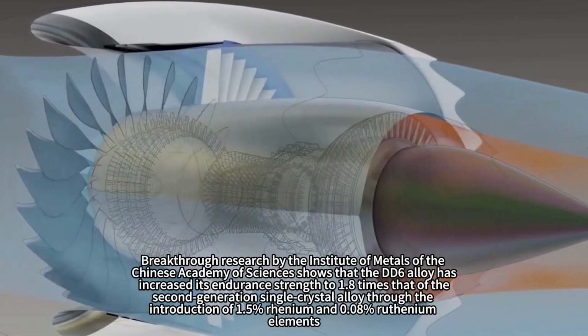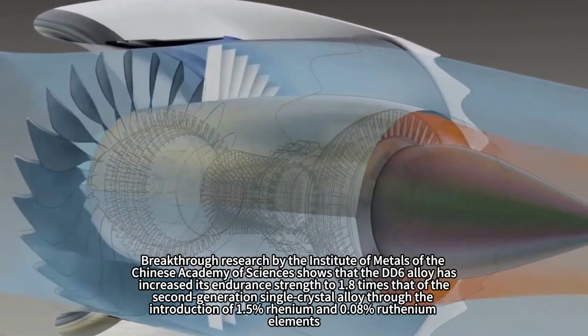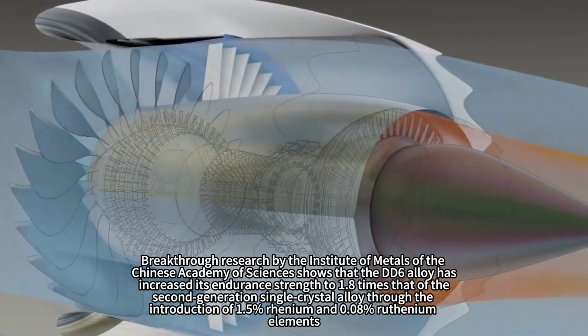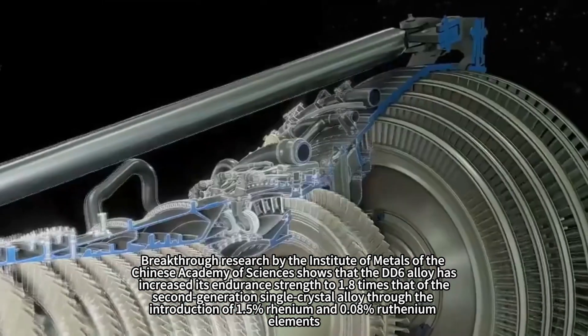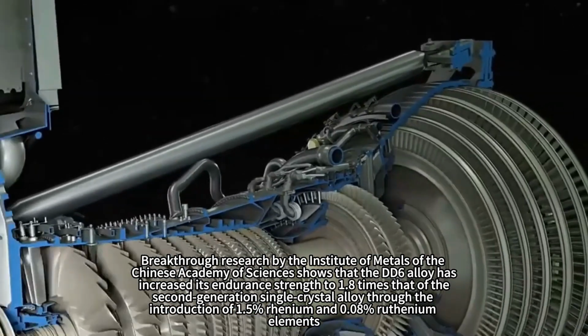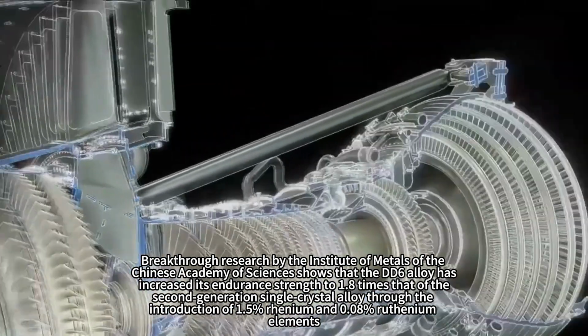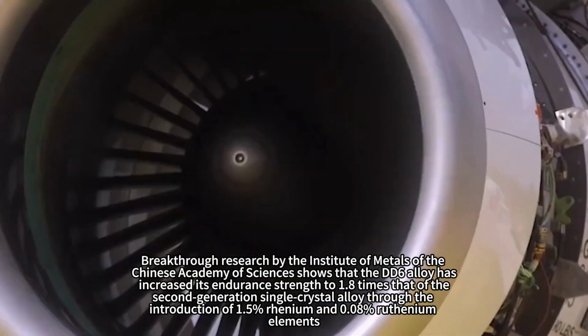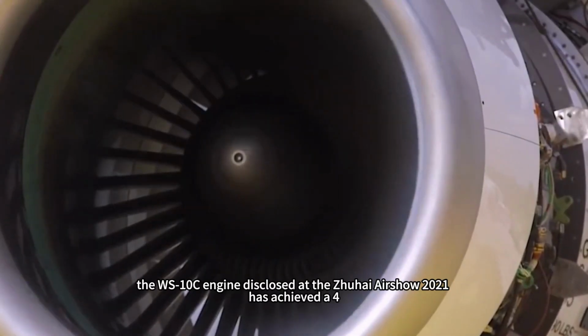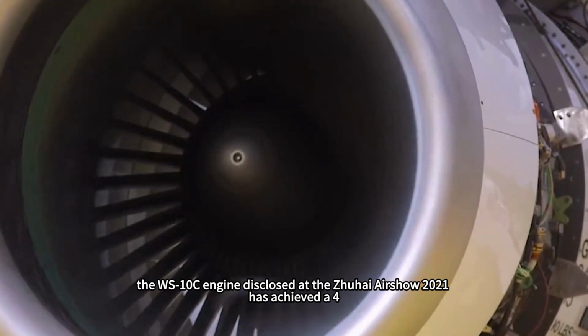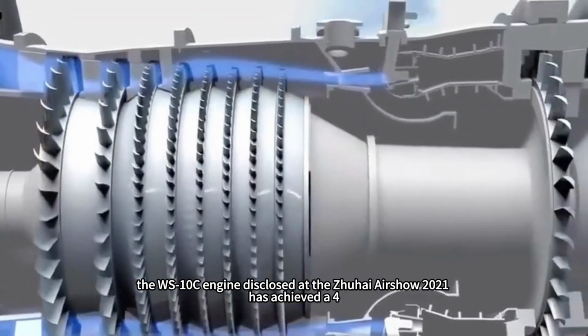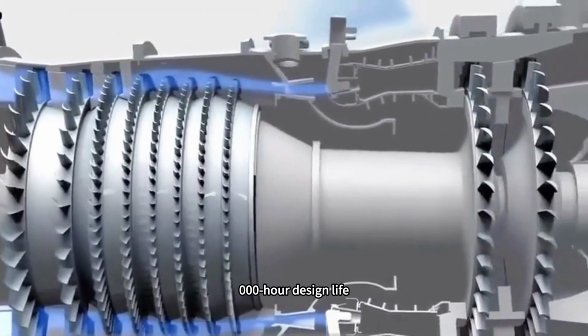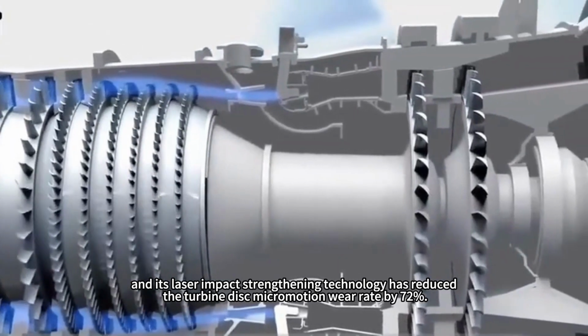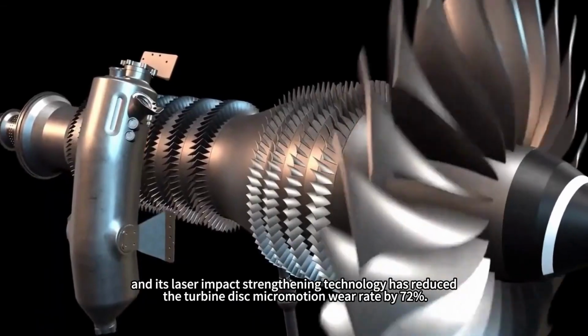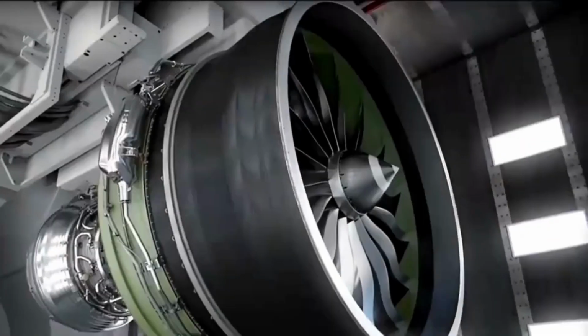Breakthrough research by the Institute of Metals of the Chinese Academy of Sciences shows that the DD6 alloy has increased its endurance strength to 1.8 times that of the second-generation single-crystal alloy through the introduction of 1.5% rhenium and 0.08% ruthenium elements. Notably, the WS-10C engine disclosed at the Zhuhai Air Show 2021 has achieved a 4,000-hour design life, and its laser impact strengthening technology has reduced the turbine disk micromotion wear rate by 72%.